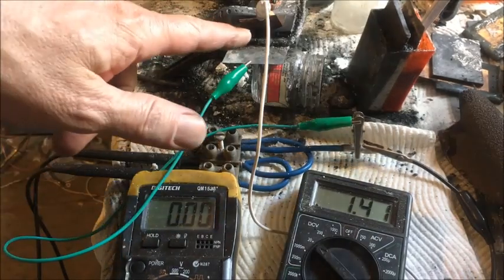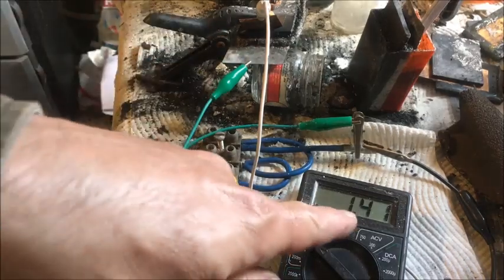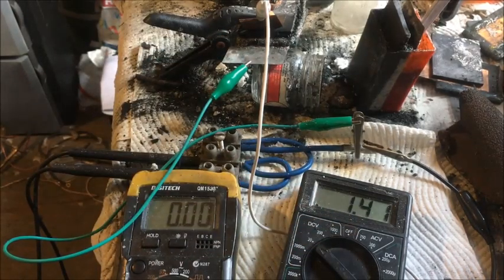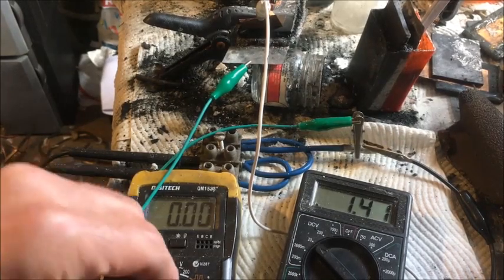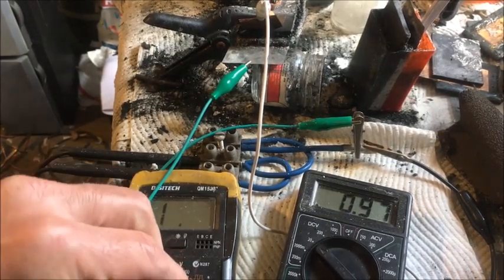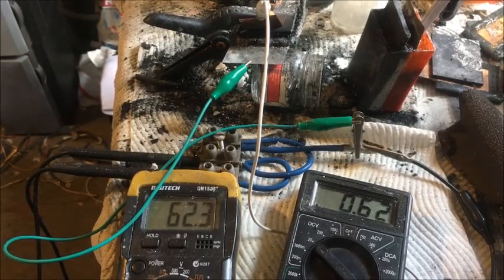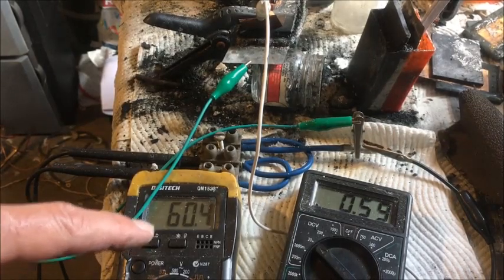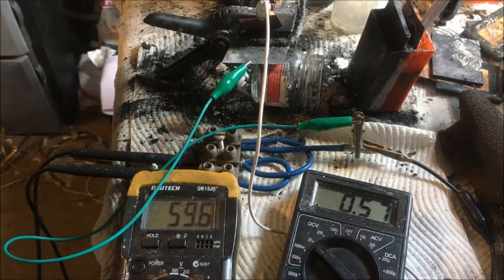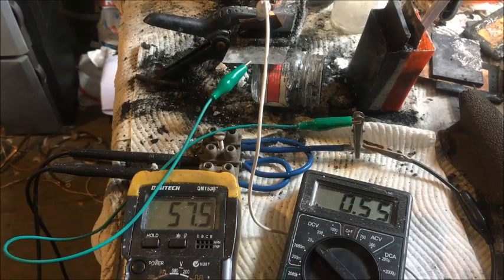Okay, just a clean of the contact plate on that zinc cell, 1.4 volts, and for short circuit milliamps, we're still not, oh, we are high, 60 milliamps on a dry cell, just sort of lightly wet about 3 minutes ago. So the cell's still alive, sort of, holding 56 milliamps.